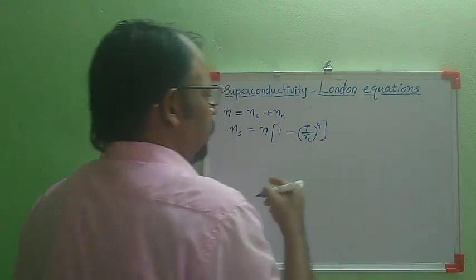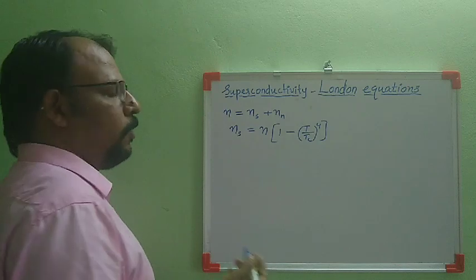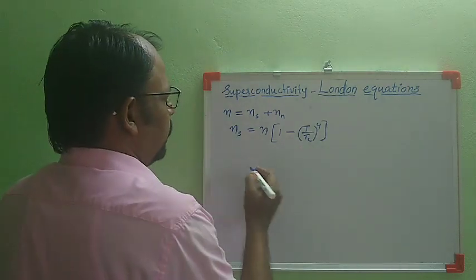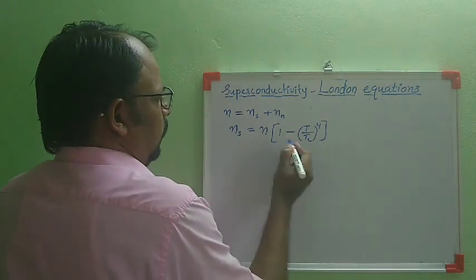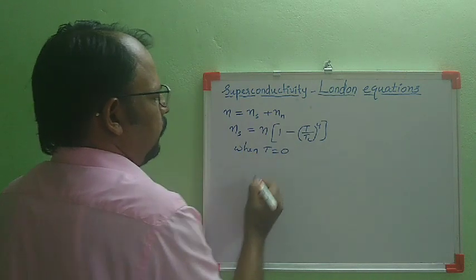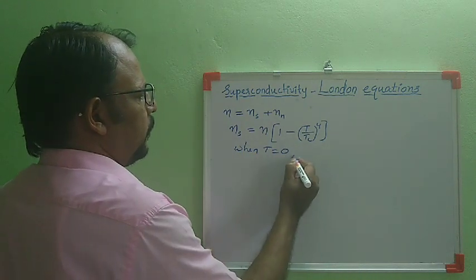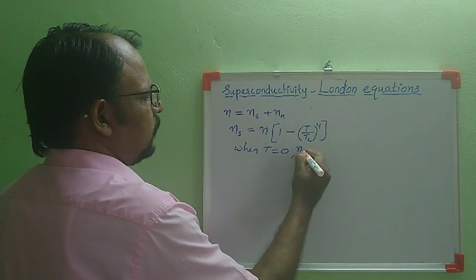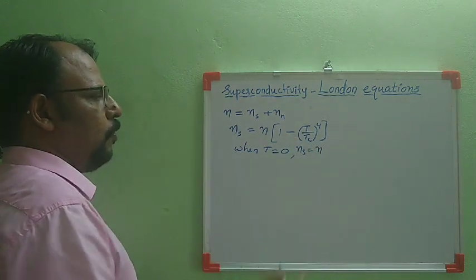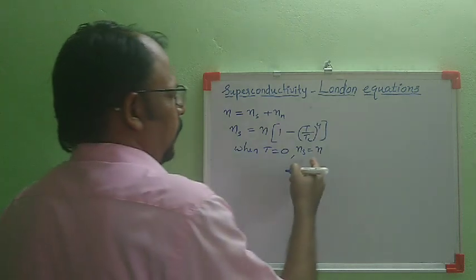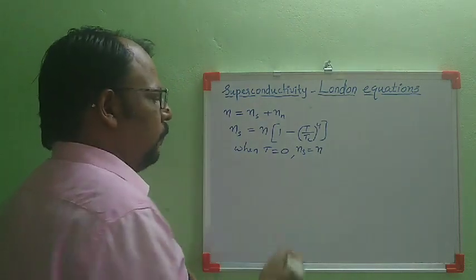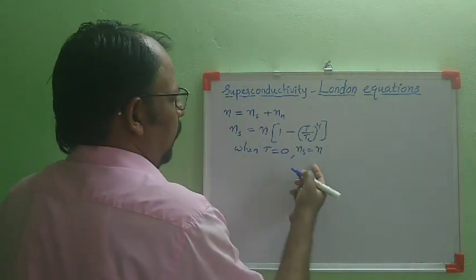They proposed this equation to explain experimentally observed facts. According to this equation, when T = 0, at absolute zero temperature, this term is 0, so Ns = N. At absolute zero temperature, all the electrons are super electrons — they are frozen to form super electrons.